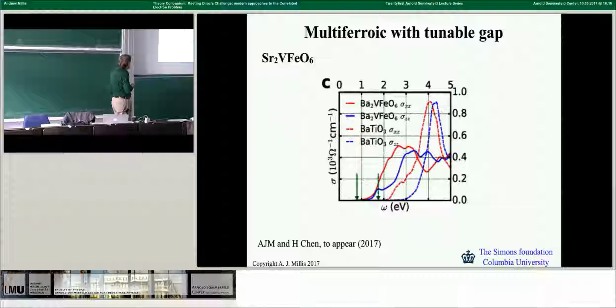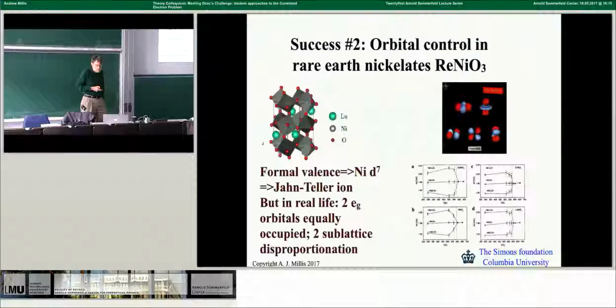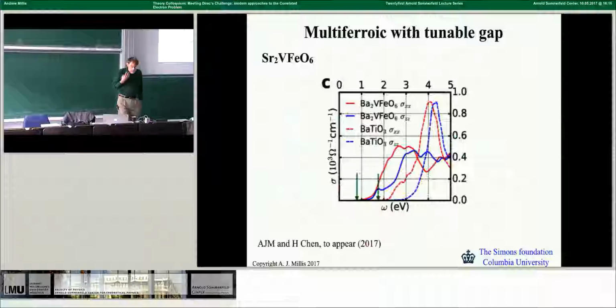All right? So this is an example of just the optical conductivity you can calculate just to show you that it is an insulator. It does have a gap. The gap is lower in energy than another technologically important material, barium titanate, shown by dots. This is useful essentially because the solar energy spectrum is more nearly here than here. So this is a band gap which is in a useful area. All right? So this kind of thing shows that at least for a certain class of properties, we're getting to the point of being able to predict structures that do things that we want them to do.